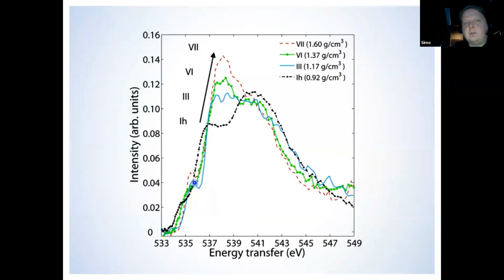Looking at this, what could be a consistent way of looking at it is that these spectral changes, which decrease the pre-edge, increase the main edge, and decrease the post-edge, are related to density, so that the lowest density ice phase has a strong post-edge, for example, and the highest density has the minimum.